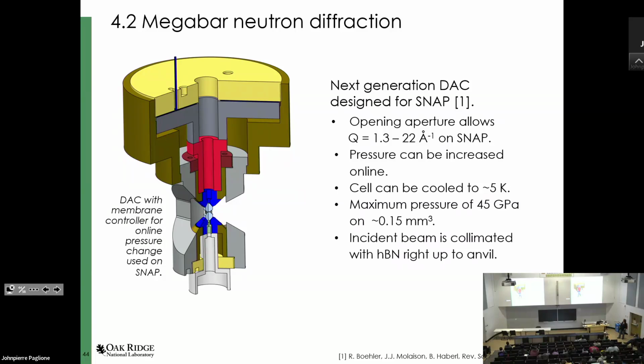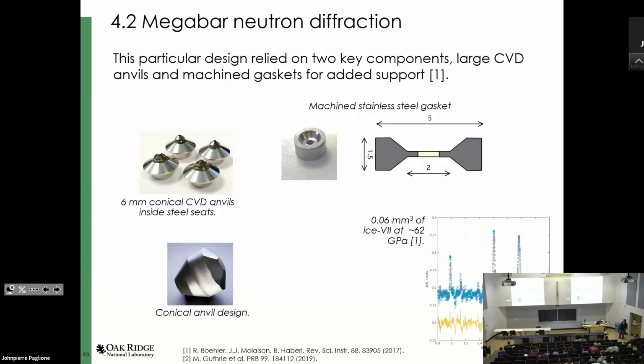Pressures were initially limited to 45 GPa on reasonably sized samples. This is what was used for quite some time across SNAP in various diamond anvil cell experiments. Here you see a few more examples. These are the CVD anvils. They were all Boehler-cut conical anvils so that we could get to the loads without the diamonds breaking. We used some pre-machined gaskets to give a little more radial support on the top of the anvil, which again helped with stability. The pressure record we managed with these cells was a little over 60 GPa, on ice yet again, but these were fully refined data.